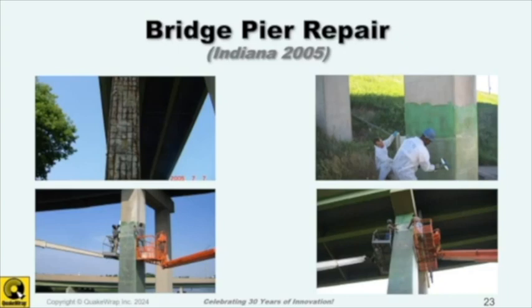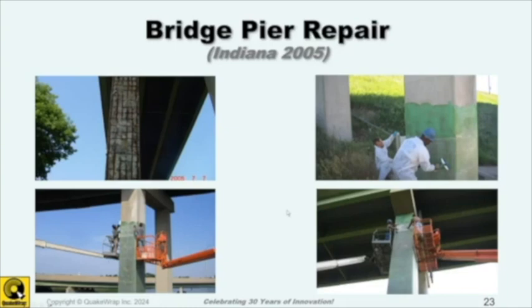This is the old way to repair a bridge column — I'll then show you the new one. This was from 2005 work we were doing in Indiana. If you have a corroded concrete column, first you clean it, then patch the concrete to make the surface flat, because you cannot wrap fabric around an uneven surface. You have to wait for the patching material to cure before you can start wrapping. In a couple of minutes I'll show you what we can do with the new system — much faster.